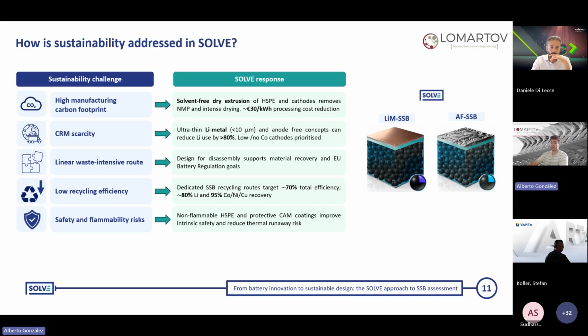Second, we are tackling material scarcity head-on through the two target concepts that you see on the right, the lithium metal and the anode-free anodes. By using this ultra-thin lithium metal, or even eliminating the excess lithium entirely with the anode-free designs, we can significantly reduce our lithium footprint. And at the same time, we are prioritizing low or no cobalt cathodes, which is vital for reducing both the environmental impact and the supply chain risks.